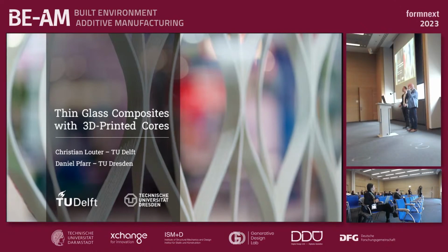Thank you for the presentation. I have a question. Do I understand right that the usage of glass with ultraviolet protection is not possible because of the gluing process? Yeah, you mean that if you have any UV blocking mechanism, that it would be difficult to use the UV curing glue. I think to a certain extent that's valid, especially if you come to a laminated glass. But the hot melt that Daniel showed in the end doesn't have this UV activation need. So that's cured by heat in the end.